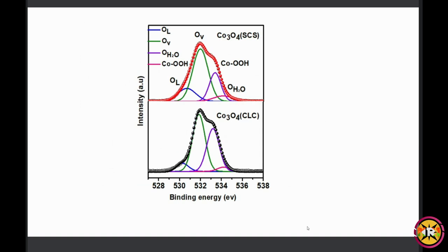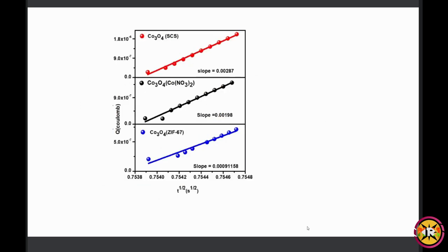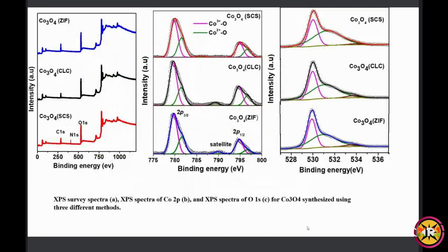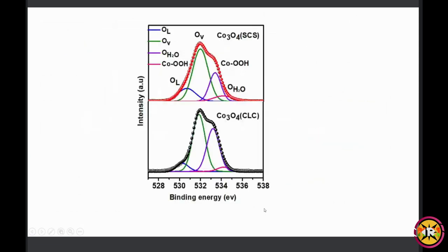And now coming to the last figure, here I have done oxygen 1s XPS after the oxygen evolution reaction. So what is the difference here? Here you can see four peaks appear, but when I did the oxygen 1s XPS before OER, you can see clearly three peaks present, but after reactions, four peaks are present. This peak around 533.5 to 534 is a new peak. Basically, this is the metal oxyhydroxide peak. That's indicating your reaction is happening, because this metal oxyhydroxide is formed in the RDS.